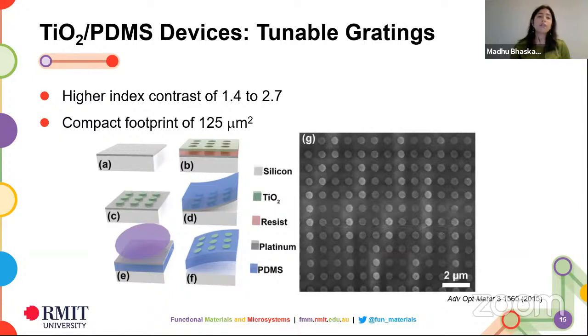Now, generally, you could never obviously take an oxide material and put it on a stretchable substrate and make various applications out of it. So given that we have this process, we were able to make these titanium dioxide devices, which we used to demonstrate some tunable grating type applications. So you can see we used electron beam lithography and we generated these little circles of titanium dioxide sitting on top of the PDMS.